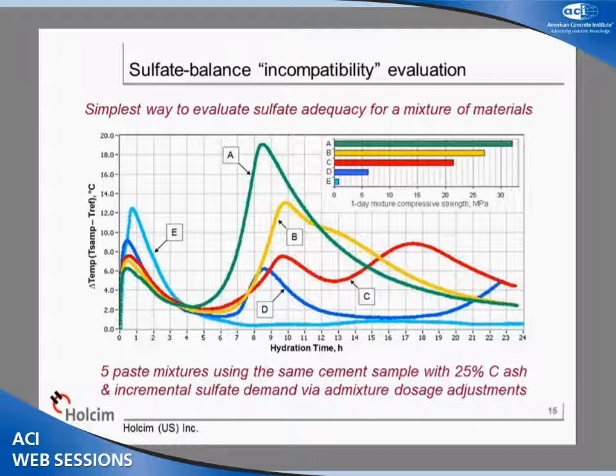And this set of mixtures was exactly the same proportions and materials with the exception of admixture dose, which was incrementally changed in an aggressive mixture at summertime concrete temperatures. And you can see in the case of the normal hydration, the green curve there, the strength produced at one day, all the way to the most extreme case for the most incompatible set of conditions, which produced virtually no measurable strength in one day and would have been a very unusual setting time trend.